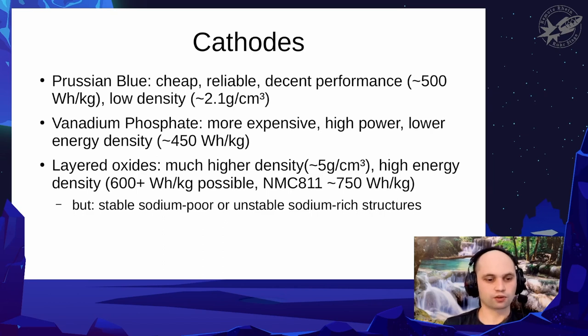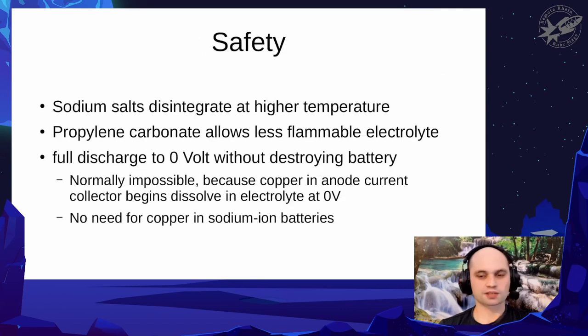The other way is you have a sodium-rich structure that is somewhat more unstable and only lasts for a few hundred cycles. But what you can do is get a structure that is kind of in between, where you get at least a bit more than 500 watt-hours per kilogram. And that has been demonstrated already. Faradion, in Great Britain, has demonstrated a material like that with about 500 watt-hours per kilogram.